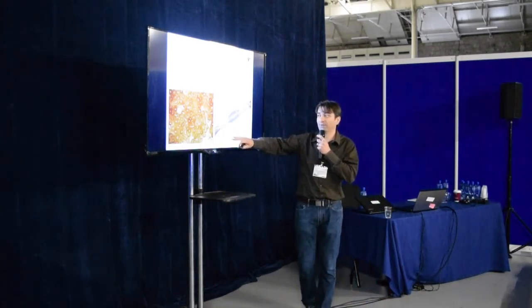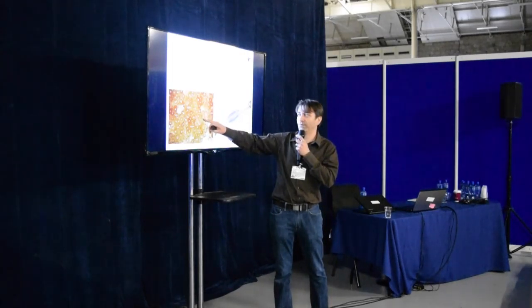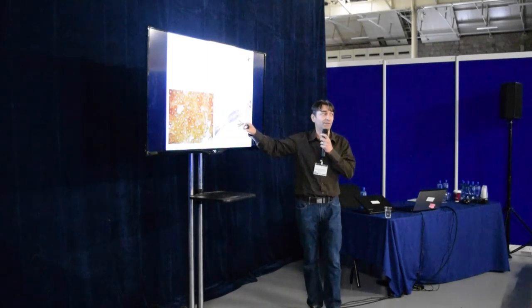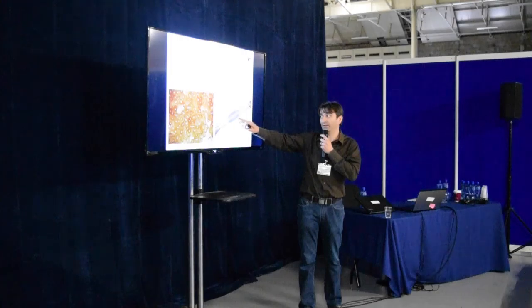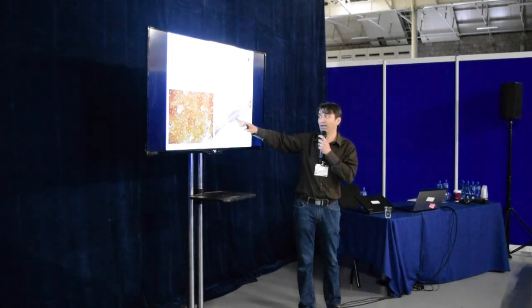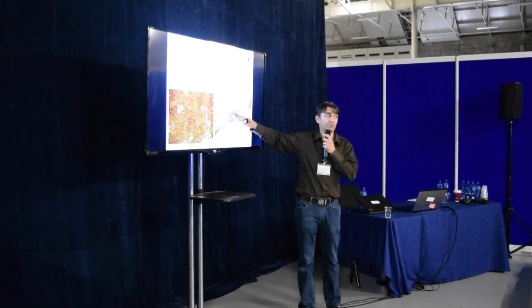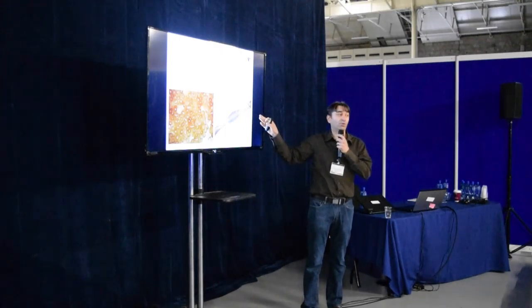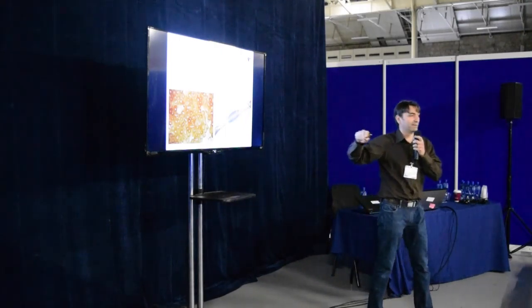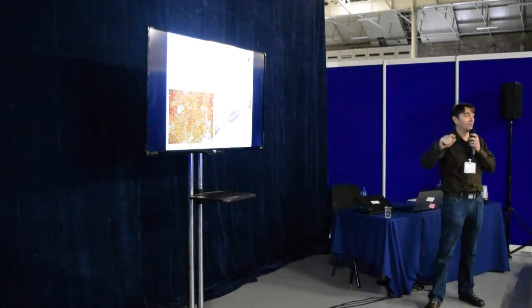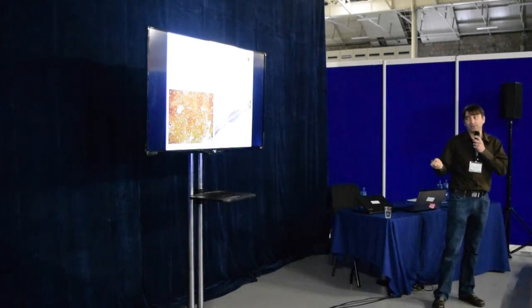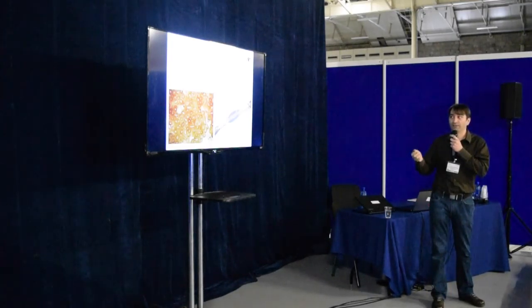And we can encapsulate it in the form of microcapsules or microfibers. And these fibers look as shown here in the image. And the reason why we don't have fully hollow fibers is to allow the crack to hit one capsule, so we can heal multiple cracks. If you have only one fully hollow fiber, then we can heal only one crack at a time. So that's the advantage of these compartmented fibers.